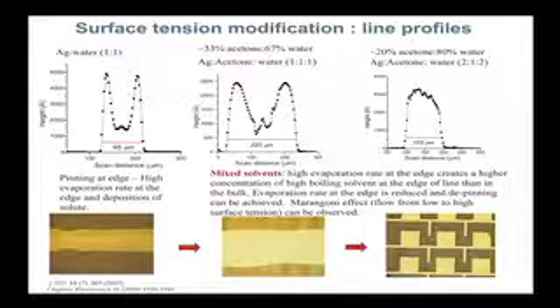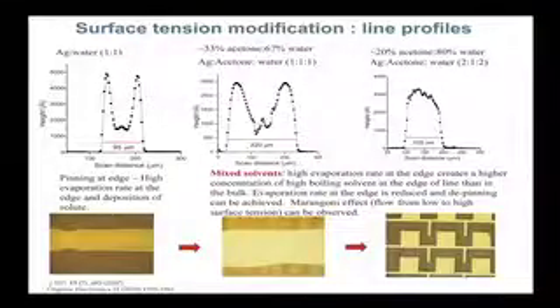Well, one thing that you can do is to change the surface energy of the substrate so that pinning doesn't happen and the drop can freely shrink as it's evaporating. Or, and in some cases this is not really desired, because that means that the solution is basically de-wetting from the substrate. Or you change the surface tension of your ink or of your material, of the solution, in order to compensate for this coffee stain effect.